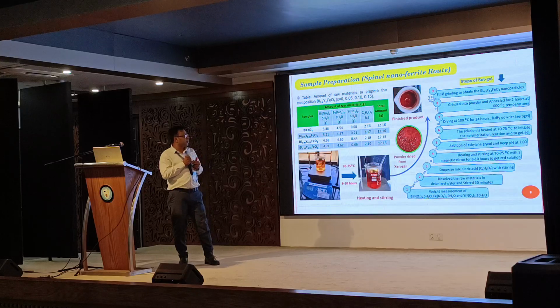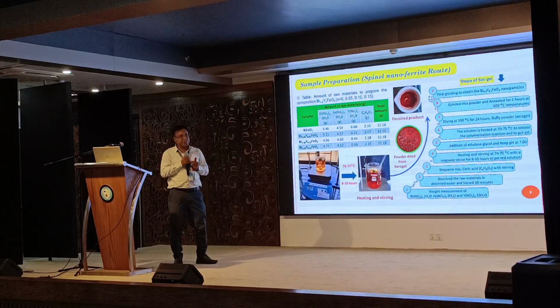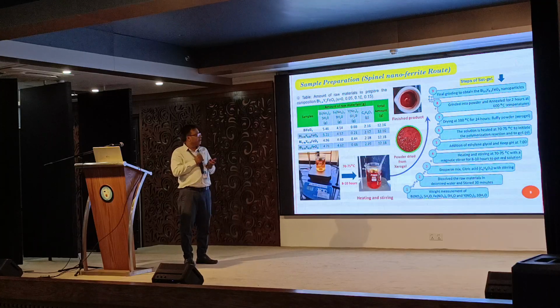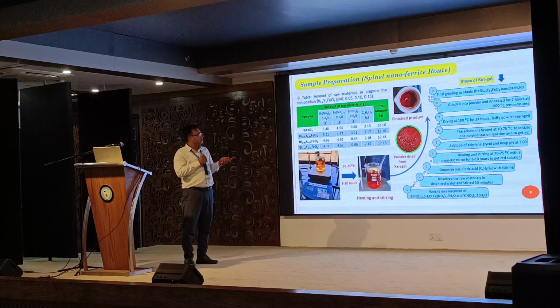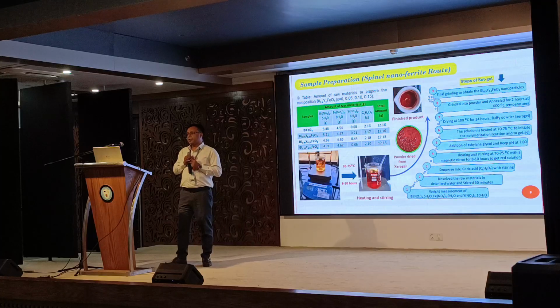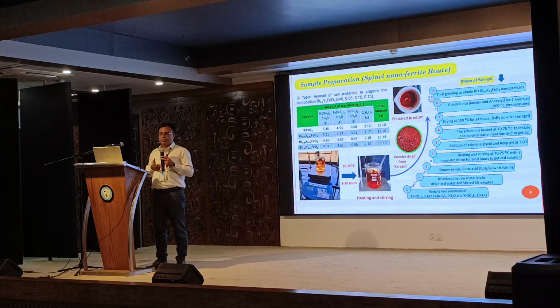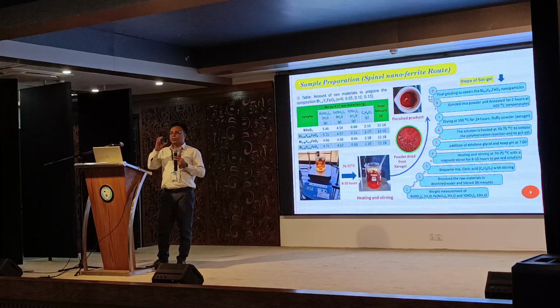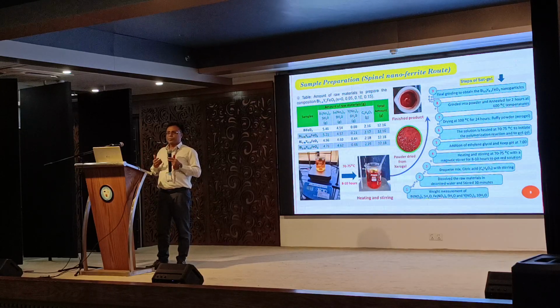Then we actually get a fluffy powder, that is the xerogel, and we have to grind it and apply some heat treatment to improve the quality of crystallization. That is, 600 degrees Celsius is enough for making it crystalline, for 2 hours, and finally we get the nanoparticles of spinel. So it depends on whatever composition we wish to make. By this process we can make nanoparticles. But what happened in this method? We did not get enough sample for our device fabrication or to integrate into our device for our actual purpose.